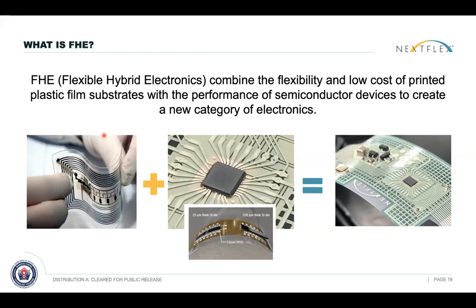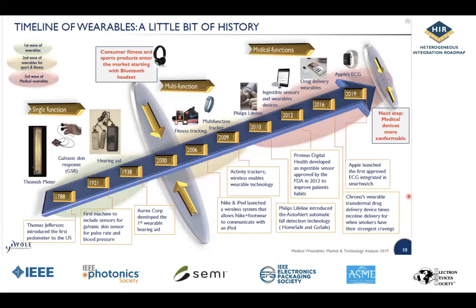And so what flexible hybrid electronics does is take the best of the printed electronics, and those could be printed sensors and devices as well, but typically printed interconnects and printed circuits. It mounts a typically unpackaged die directly to the surface, taking great care to recall that dies are rigid and the ceramics and plastics we're working with are flexible, so they have to be thin so that they will conform and the interconnects will be robust. And ultimately create, as you see here, an early prototype of an all-FHE Arduino controller, something much more consistent with what could be laminated into an article of clothing or a wearable device that would allow communications, data acquisition, and all these kinds of things centered in one generic platform, and ultimately something that could be manufactured in high volume like Arduino controllers are today.